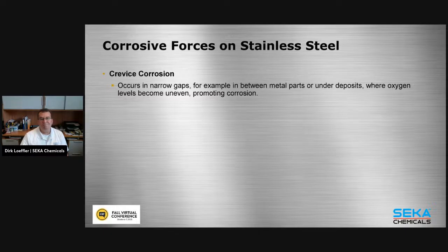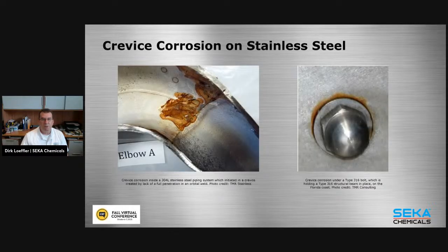Crevice corrosion, I don't really see this that much, but when you have two pieces of stainless steel joined and there's a gap in between, you have uneven oxygen levels in there. We talked about that the oxygen is very important for maintaining the passive layer. It does promote corrosion. Generally this looks like this here. So this is, for example, a crevice corrosion that happened inside an improperly done weld.